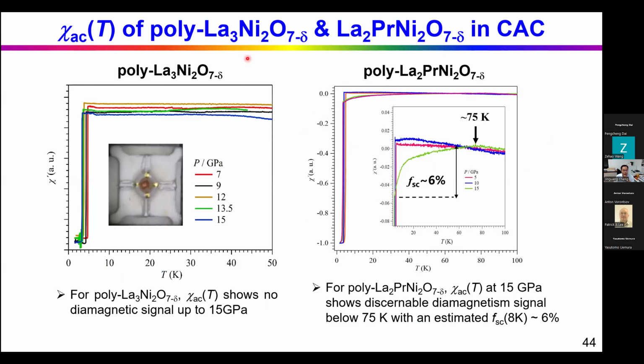So we performed the AC susceptibility measurement on these two samples in the cubic anvil cell. For this undoped sample, we measured up to 15 GPa and we only observe the transition from the lead. There's no signature of a transition from the sample. But to our surprise, for this doped sample at 15 gigapascal, in addition to the transition of lead, we observe this very broad drop in the susceptibility, starting from 75 Kelvin. By comparing this drop of the sample and the lead, it has a volume fraction of about 6% at 15 gigapascal. So this is quite encouraging.